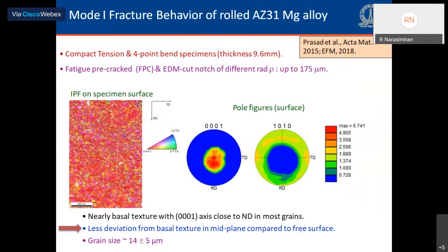Now next, let me turn to some experiments which we did using rolled AZ31 magnesium alloy. Here we conducted experiments using both compact tension and 4-point bend specimens, thickness around 10 mm. One of the ideas here was to look at the effect of stress triaxiality. Triaxiality is a very important factor as far as fracture of magnesium is concerned. So we varied the notch root radius and considered different EDM cut notches, as well as fatigue pre-crack specimens (FPC) in our experiments.